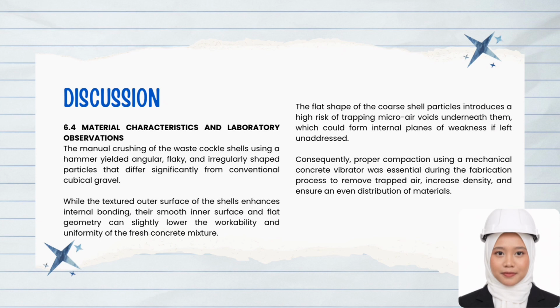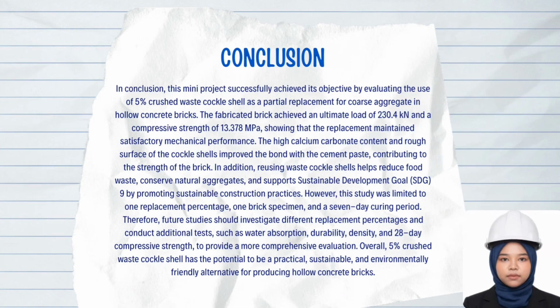Therefore, proper compaction using a mechanical concrete vibrator was absolutely essential to remove trapped air, increase concrete density, and ensure an even distribution of materials. In conclusion, this mini project successfully achieved its objective by evaluating the use of 5% crushed waste cockle shell as a partial replacement for coarse aggregate in hollow concrete bricks. The fabricated brick achieved an ultimate load of 230.4 kN and a compressive strength of 13.378 MPa, showing that the replacement maintains satisfactory mechanical performance.